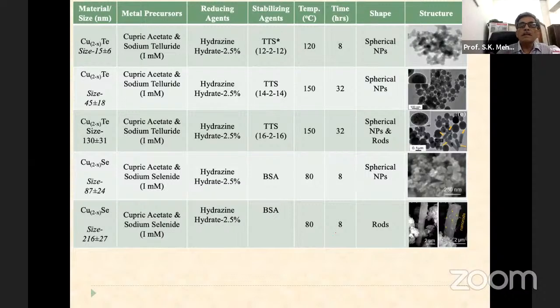This work, most of the work was done by one of the postdocs. She did her postdoc with me, and she created so many of these particles, nanostructures. So this table shows you copper telluride, the size range. You have metal precursors which we have used, metal acetate, sodium telluride. You have used hydrazine hydrate as the reducing agent, and then we have a stabilizing agent, which was used at temperature 120, time 8 hours, and we got the shape.